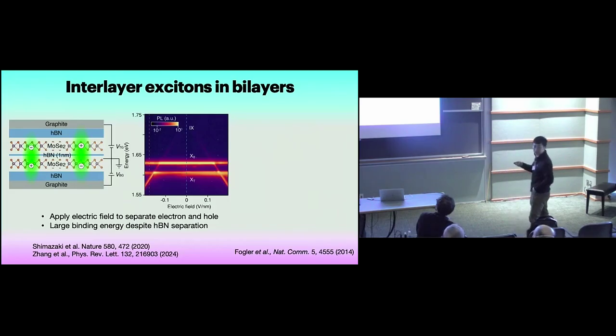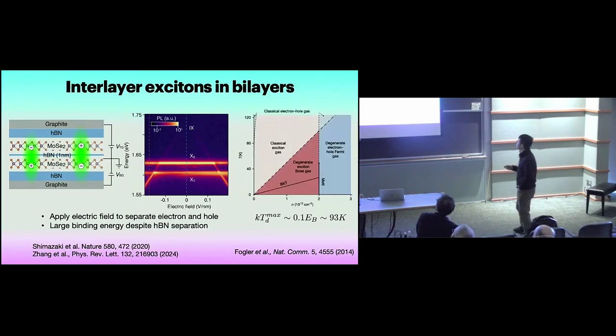This was pretty challenging to do before our experiments. What this could allow us to do is to explore this exciton condensate region. Because the interlayer exciton separates the electrons and holes, they have very long lifetimes, on the order of nanoseconds to even microseconds. So potentially we can create a high density of excitons. And we also measured the binding energy of this interlayer exciton and found it to be pretty high. It's around 80 milli-electron volts, even though you separated these 2 layers. So this allows us to estimate the maximum condensate temperature to be around 93 Kelvin. So potentially we can create a very high density of interlayer excitons and explore this region.